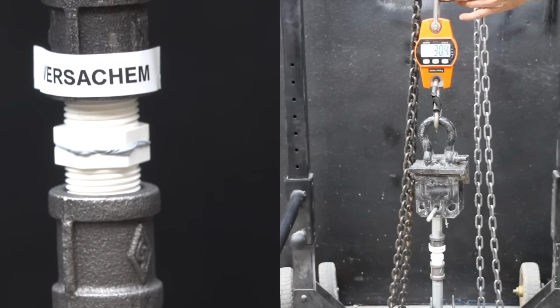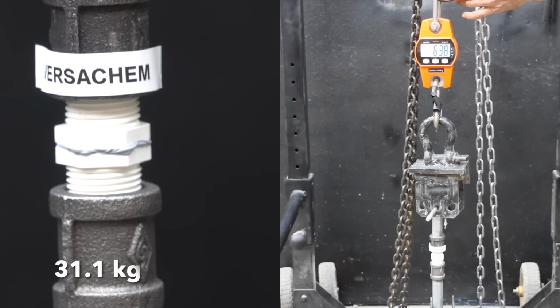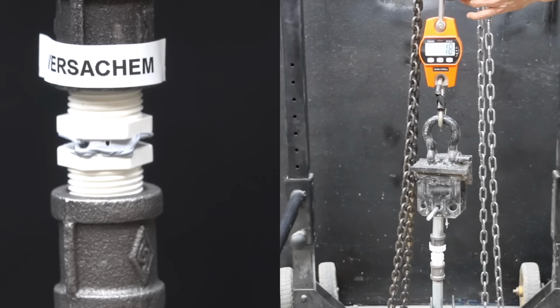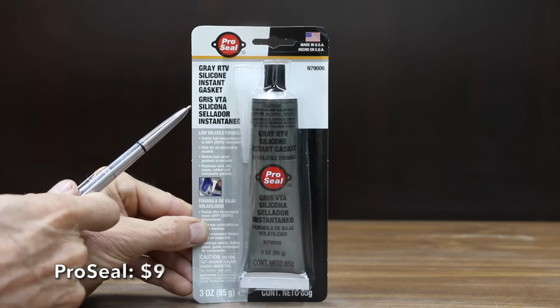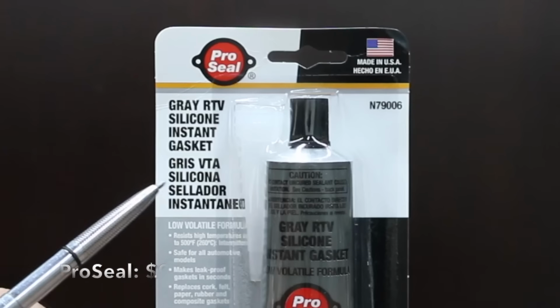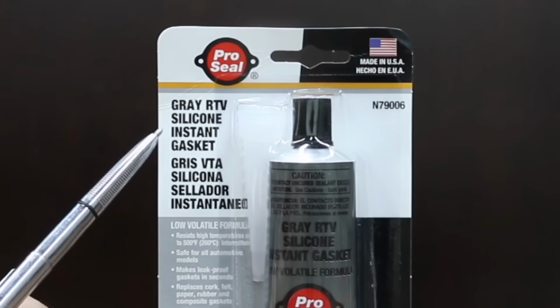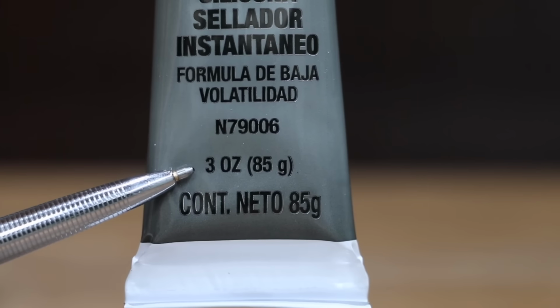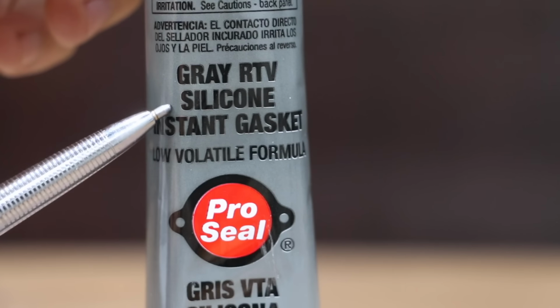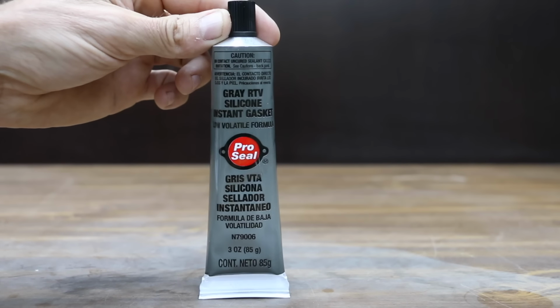68.6 pounds on the third test piece for an average of 68.7 pounds to move into the lead over the Permatex Ultra Grey. Also, the price of $9 for 3 ounces, or $3 per ounce, is this Pro Seal Grey RTV Silicone Instant Gasket. It's designed to replace cork, felt, paper, rubber, and composite gaskets. The Pro Seal is made in USA.